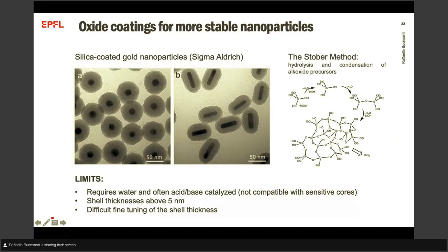The problem with this silica coating is that it's synthesized with the Stöber method, which is based on hydrolysis and condensation of an alkoxide precursor. Here, basically, water is required, and this is not compatible with sensitive cores, such as the perovskite nanocrystals.